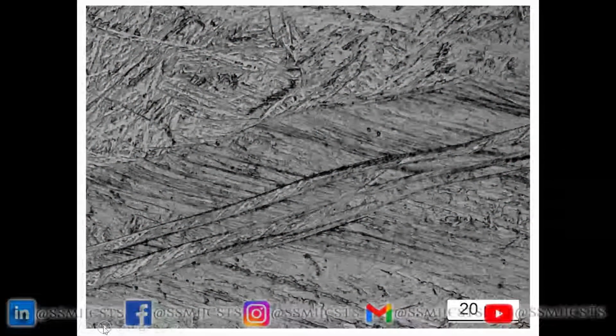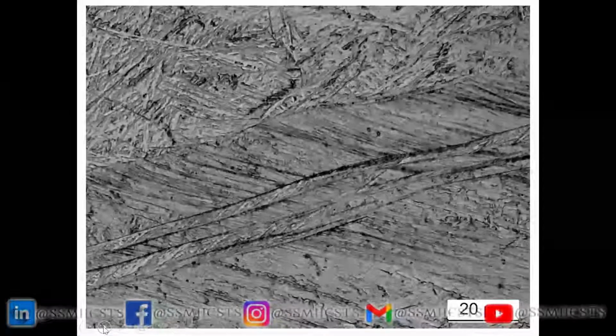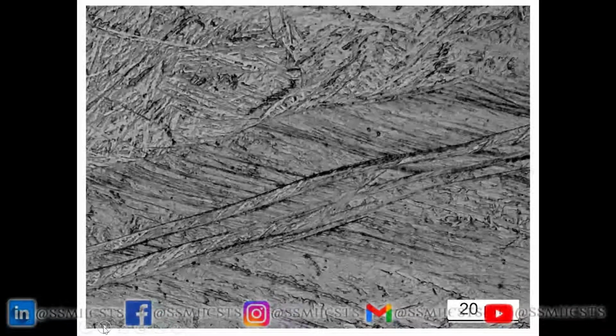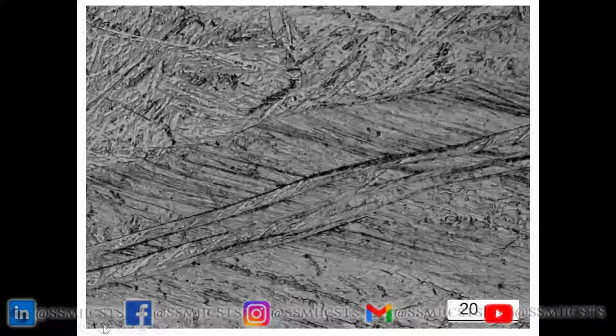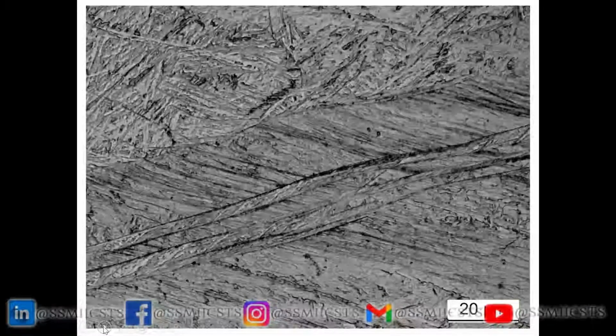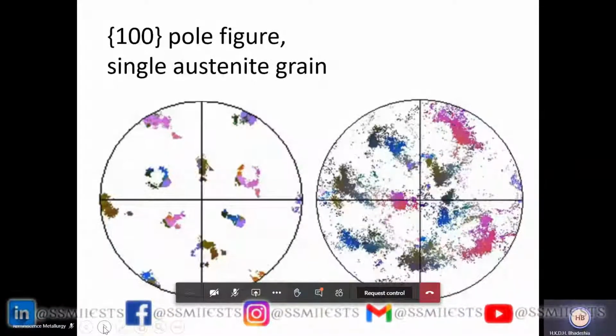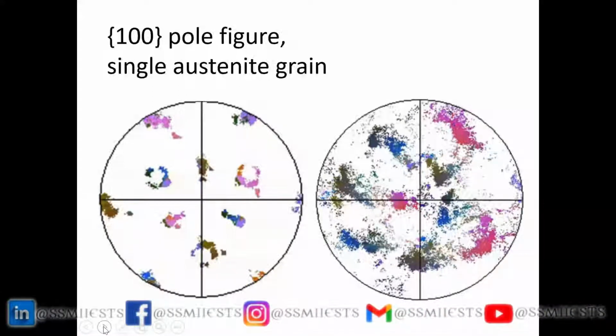shows the beautiful structure obtained at Tata Steel in India of severely pancaked austenite grains. Okay, now not only are they severely pancaked, but there are lots and lots of deformation bands within each of those pancaked austenite grains. So what that means is that you've reduced the grain size dramatically. And just to show you the effect, if you go to the next slide, these are EBSD figures from a single austenite grain. On the left-hand side, the grain is undeformed.